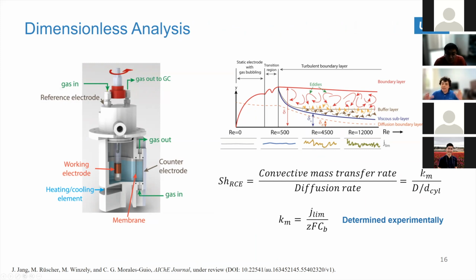So that tells us, if the bulk concentration is a certain concentration, what should be the concentration at the surface of the electrode, because I'm limited by how fast mass can move, as given by this Km value that we can change through the rotation. There is also a dimensionless number to describe the mass transfer coefficient, and that is the Sherwood number. The Sherwood number is the ratio between convective mass transfer and diffusion rates. And so this is also a dimensionless unit. What is important here is that this Km value can actually be measured experimentally.